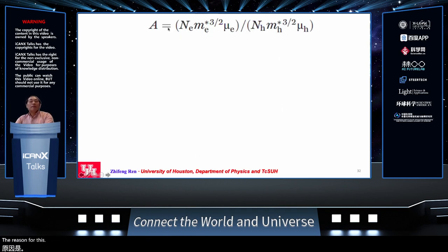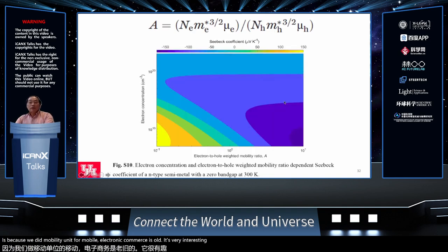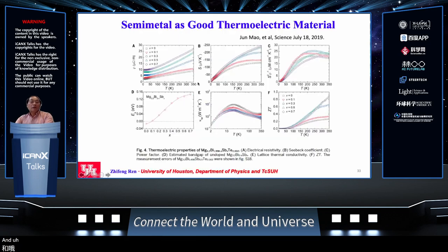The reason for this very high performance of a semi-metal is because the weighted mobility, electron versus hole, is very interesting. This material's is very large, larger than 10, which is why it gave us a very high Seebeck coefficient. With further optimization with some antimony, we opened up a gap, even with 0.7 antimony, and the gap is still very small, less than 0.15. And of course, the ZT of this material at room temperature is about 0.7, 0.8. That is very much comparable with bismuth telluride.